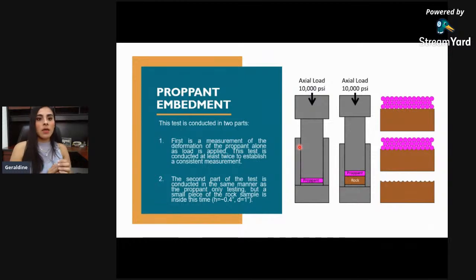So the proppant embedment is conducted in 2 parts. The first part is just a measurement of how your proppant will compact. In this case, you use a proppant embedment cell like this in the picture, and you just apply proppant to the cell. You do all the tests, apply 10,000 psi of axial load in a time of 60 minutes, and then you analyze how your proppant suffers the compaction or accommodates in the cell.